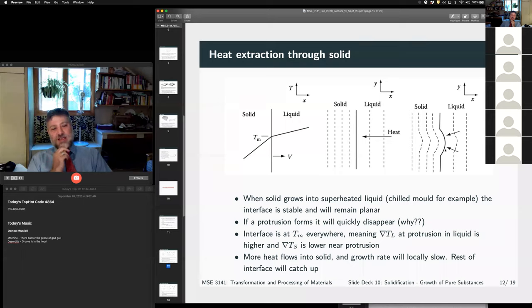And the velocity is directly proportional to the conduction term. So if we're conducting less heat, that means this part of the bump is going to slow down and the rest of this interface will catch up. So if we're conducting heat through the solid, we're always going to remain at a planar interface, right?